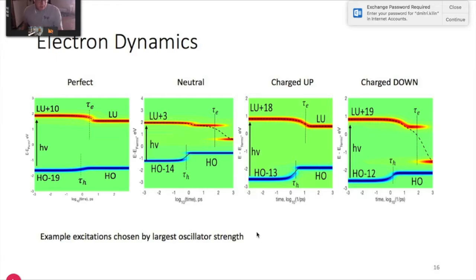So with the perfect system, we're looking at a HOMO minus 19 to a LUMO plus 10 transition. And so here, the electron relaxation is somewhat close to just under 4 picoseconds, whereas for the hole relaxation, it's just under 1 picosecond. So I would say they're relatively scalable to experimental results, but the charge carrier lifetime, the difference between the electron and hole lifetime isn't very big, which isn't necessarily what you might want for collection of the charges.